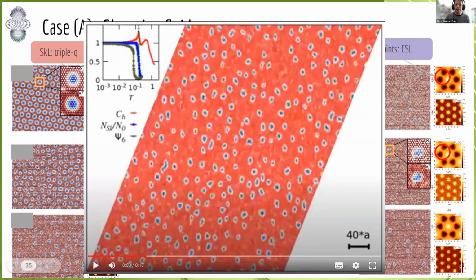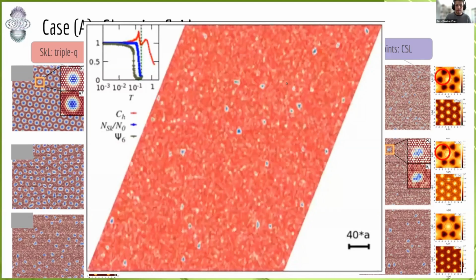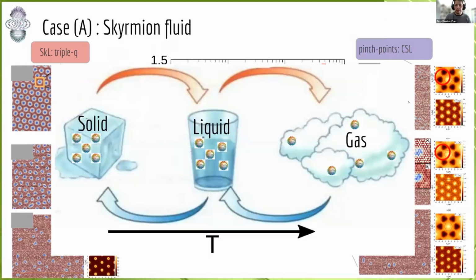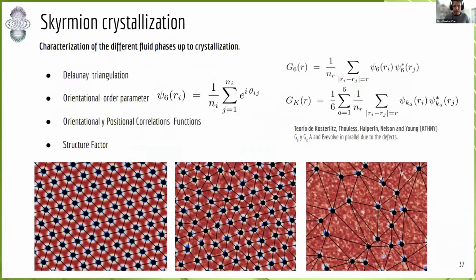Why do we have this situation? The main point here is this red background. This red background is a chiral spin liquid state. It's a ferromagnetic disordered state with dipolar correlations. Because of this situation, we study the possible transition between these three phases or fluid phases: solid, liquid, and gas of skyrmions.